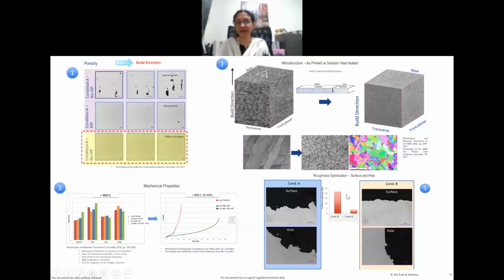And remember, all these were done in tandem in less than 1 year's time frame. So you go and evaluate the mechanical properties. Again, it's a very busy slide, but the fact I'm trying to show you here in item number 3 is 3 or 4 points. One is to look at the anisotropy of mechanical properties. Yes, additive manufacturing, by the fact that it is a layered structure, you tend to build an anisotropic structure, whether you like it or not. Anisotropy in terms of vertical, transverse, at 45 degrees in terms of mechanical properties, not like a forged structure. Maybe akin to a rolled one, where you do see anisotropy, texture, and mechanical properties. So that you need to watch out.